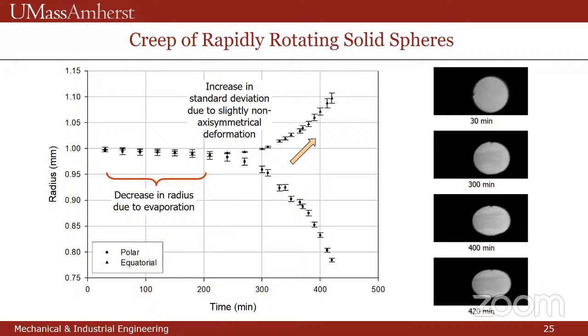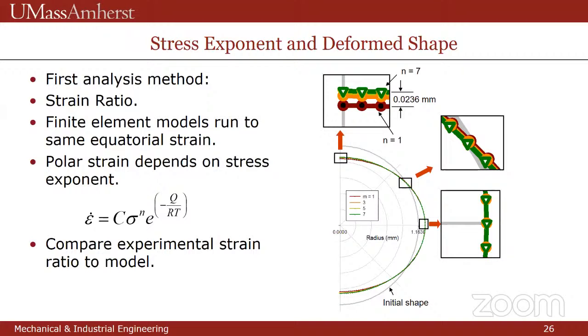Interpretation, however, is a little trickier. So we used a finite element model to run different combinations of parameters to the same equatorial strain. And you see that for the same equatorial strain, you get different, very slightly different polar strains, depending on the stress exponent in the equation.